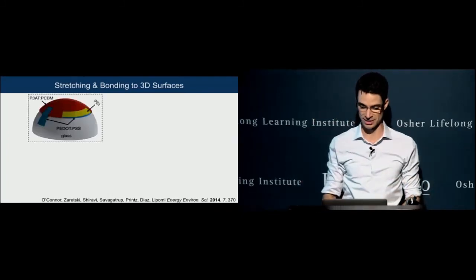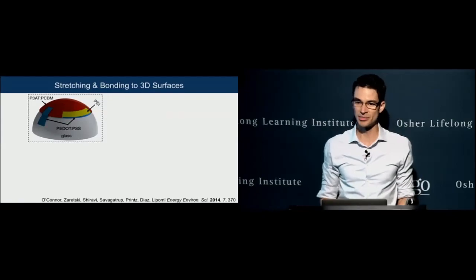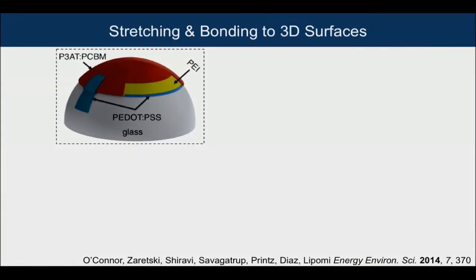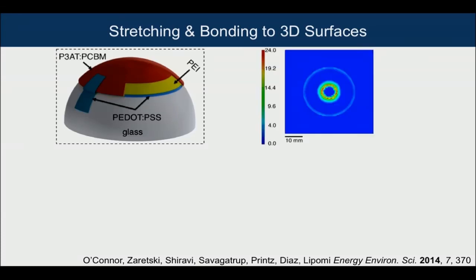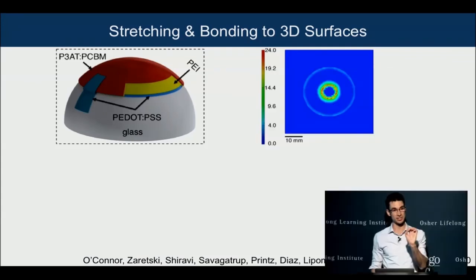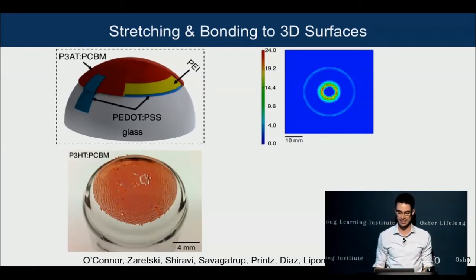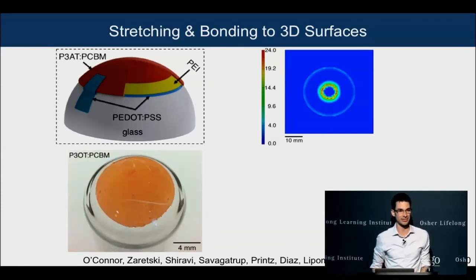It needs to stretch out in order to get something onto even something as simple as a hemispherical surface. So what we wanted to do is make this R2-D2-like solar cell. And it's basically a normal solar cell, except that we had to stretch out the material in order to get it to be this shape. So if we do a model, we found out that we needed a certain amount of strain. It turns out we needed to stretch it at maximum by 24% in order to get this thing to bond. And we found that the shorter side chain gave this cracked version, and the longer side chain gave us this intact, uncracked version.